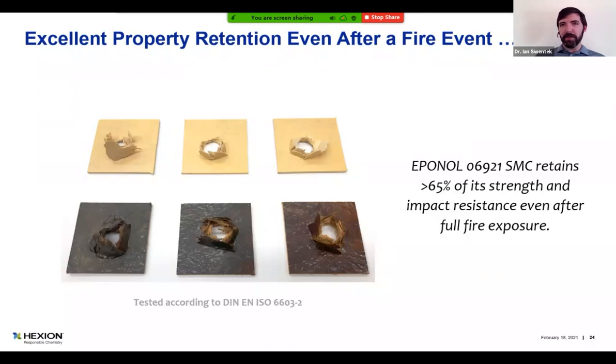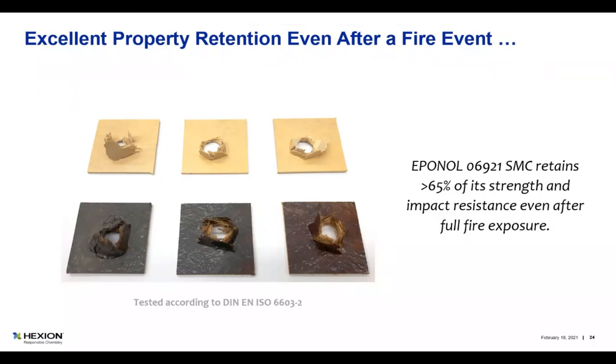Questions, Shashank, that I asked you to pause on? No, I think we can continue, but I have a quick curiosity here. The flame temperatures in the video you showed reached 700 degrees or higher? Right. There's always a question on temperature. 700 Celsius is the average temperature the surface of the enclosure faces. Most octane fuels burn at around 900 to 950 Celsius. But given the test requirements being a half meter away from the surface of the enclosure, the actual surface temperatures are around 700 Celsius on average.